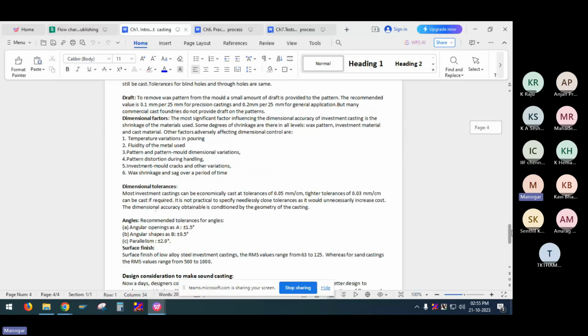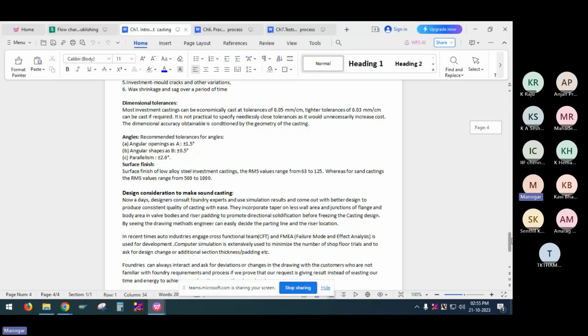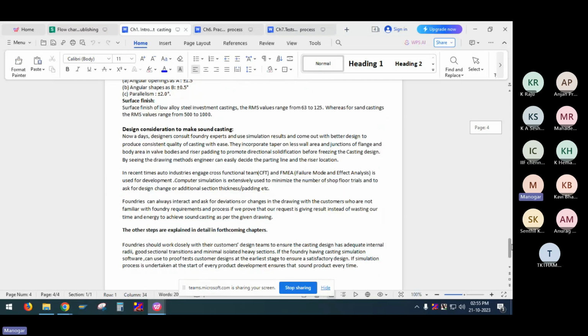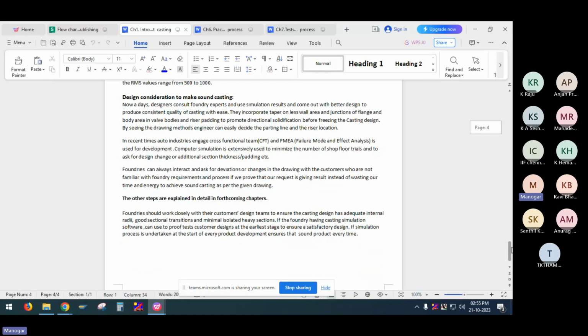Some blind holes can be made. Even though for small parts there is no need for draft, for bigger parts we need a draft, that is 0.1 mm per 25 mm, but it is more in sand casting and other processes. So that is the advantage in investment casting. And the dimensional tolerances possible in investment casting are angular plus or minus 1.5 degrees and parallelism 2 degrees. Solidification is already told. To make a sound casting, we need a fillet radius and sharp radii should be avoided, and wherever based on simulation results, design changes can be considered as per the requirement.